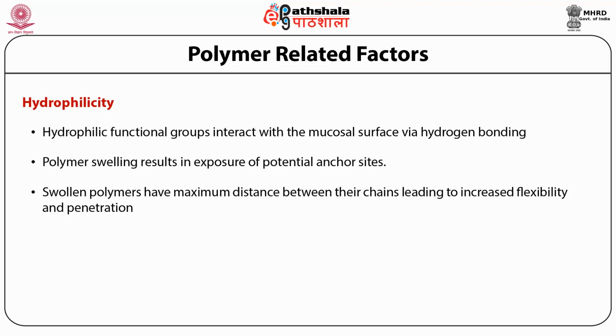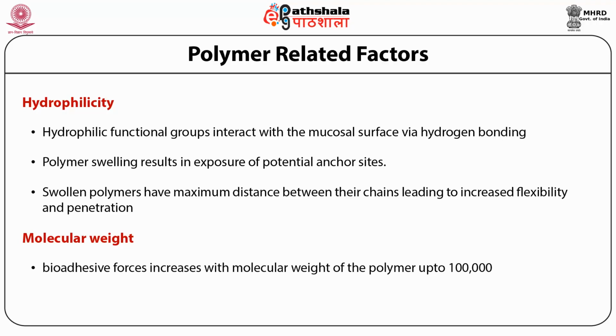The second factor, which is directly having the effect of the polymer choice, is its molecular weight. The mucoadhesive ability of the polymer depends on its molecular weight. The bioadhesive or mucoadhesive force of the polymer increases up to 1 lakh with the molecular weight. However, no further enhancement is observed beyond this value.